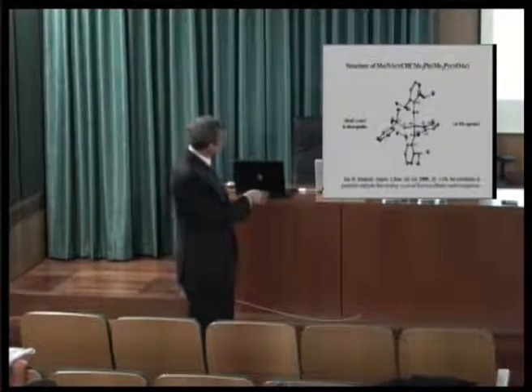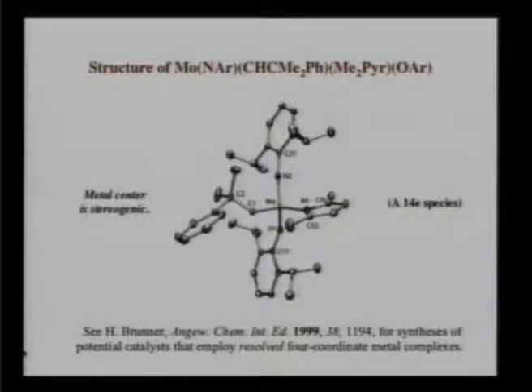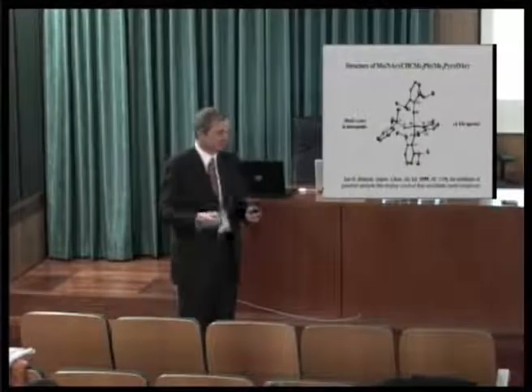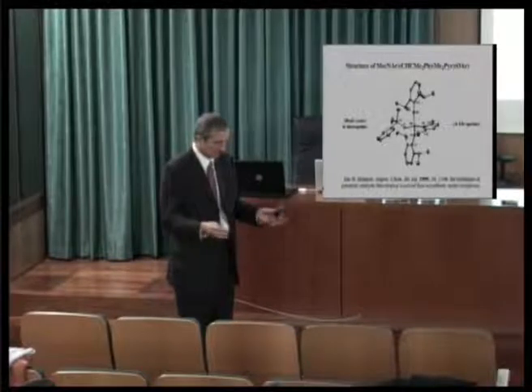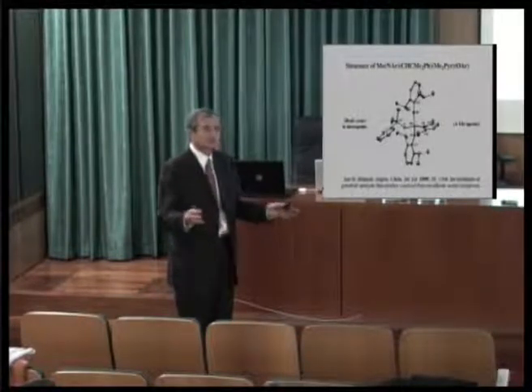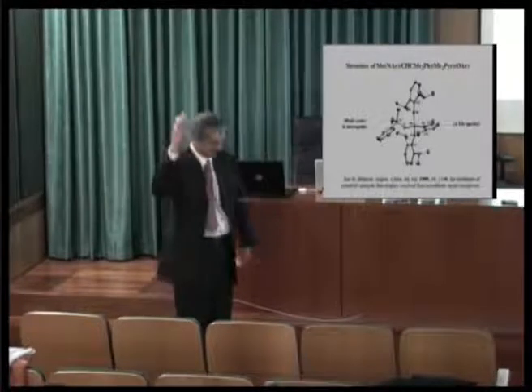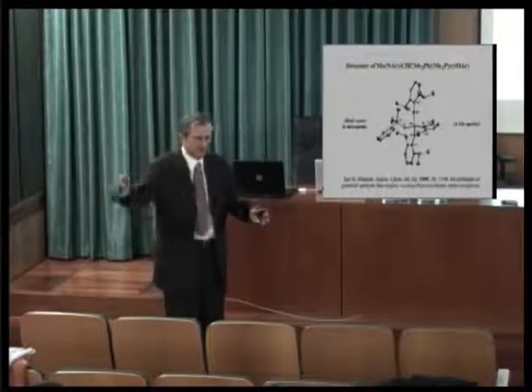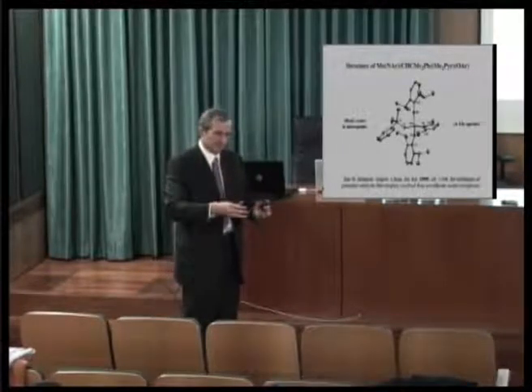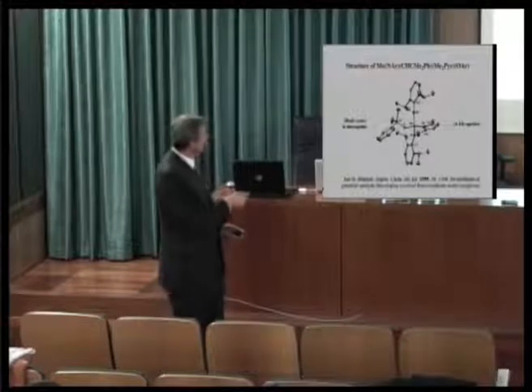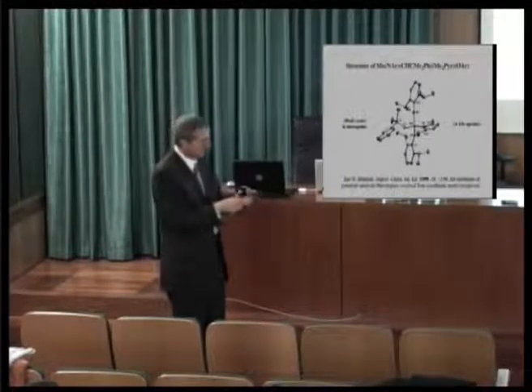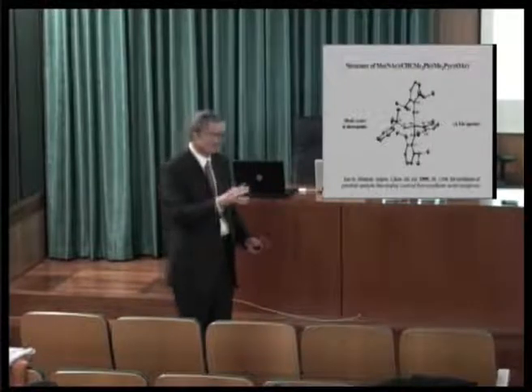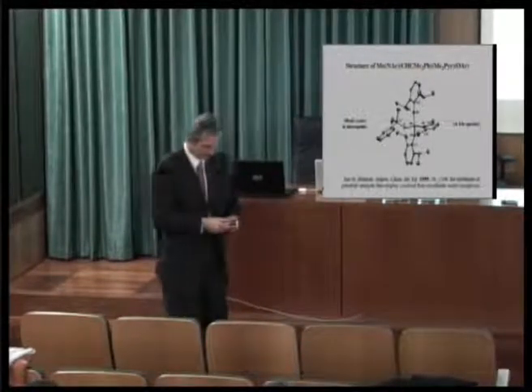Now, a man named Henry Brunner had the idea that chirality at the metal, if you could use it for a catalytic reaction, was the most powerful determinant in an enantioselective reaction, which usually, after all this time, decades, really depends on steric factors, some sort of chiral ligand that sterically prevents a substrate from attacking the metal one way versus another. Here you have 4 different groups. The substrate will attack the metal on one of the 4 faces of the tetrahedron and form a 5-coordinate intermediate.